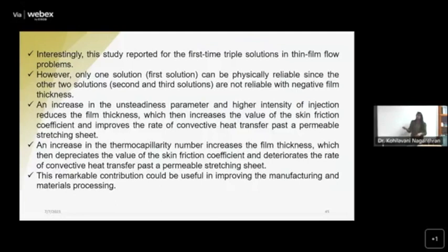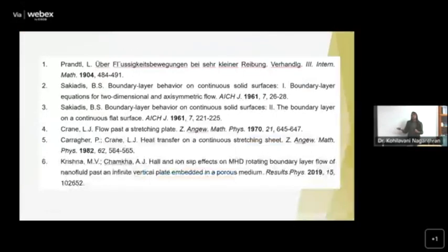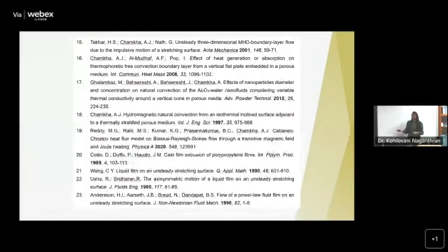And the increase in the unsteady parameter and higher intensity of injection reduces the film thickness, increases the friction coefficient, and improves the rate of heat transfer. And then the thermocapillarity is found to increase the film thickness, reduce the skin friction coefficient, and reduce the rate of heat transfer. So this is very important for material manufacturing and material processing, especially in the coating. Here are my references. Later I'll be sharing the slides with you guys.